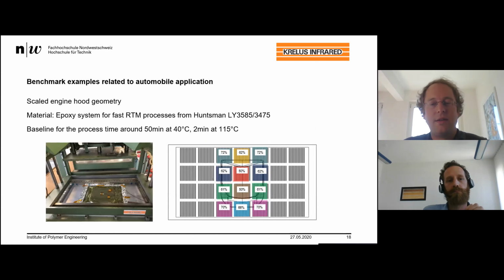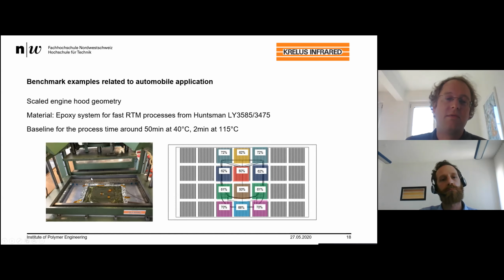So the second trial we performed was with an epoxy system which reacts really fast. And there the approach was that we apply kind of preheating, where we have a process window with a stable condition to fill the part. And then we went up to the curing temperature really fast, and this resin system needs 2 minutes to react.